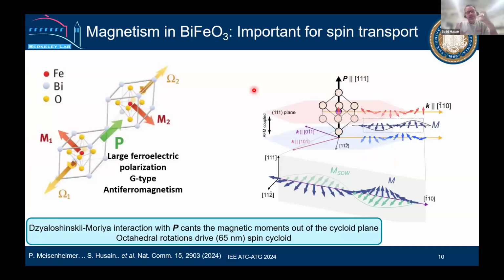It's a little bit of a complicated structure, but this is the bismuth ferrite structure. You have M1, M2. So this is one lattice of bismuth ferrite, and the structure is, if you see my hand, elongated in some direction, and that's the direction of my polar order. You have an iron in the center, bismuth on the corners, and oxygen in yellow. So using two nearby unit cells, we can explain that M1 and M2 are coupled antiferromagnetically, because of the DMI, because of the structural inversion asymmetry in the material and the polar order.